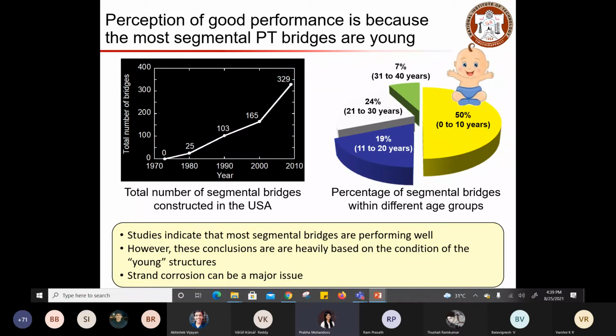So for the current survey, the study indicates that the available segmental PT bridges are performing well. Why? Because those are relatively young. Because of that, you are not noticing the damages or deterioration in the young constructed structures, right? However, the conclusions were also made based on the condition of the young structures. So that means you are not actually determining the condition of long-term performance of such pre-stressed concrete structures.